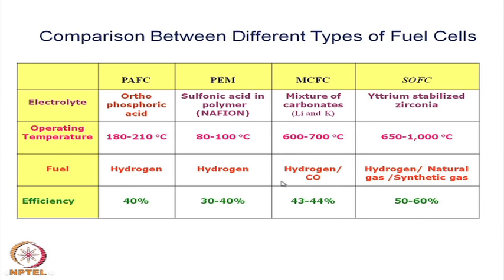So far as carbon monoxide is concerned, there is no platinum catalyst here. Both of those need some platinum catalyst. We are not going into the details of why the platinum is needed, but without a very fine dispersion of platinum catalyst, this kind of system does not work. We do not need any platinum catalyst here; the catalyst is an oxide catalyst. So, this can operate with hydrogen, natural gas, even synthetic gas. So, one can generate synthetic gas from coal and then burn it. One has to find out what the total overall efficiency is, because efficiency is one of the driving forces for developing this kind of system.